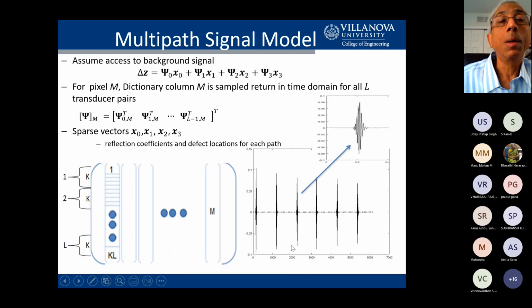Well, again, for each path, you construct a dictionary matrix. And for each path, you have a defect unknown vector. Of course, these X0, X1, X2, X3 must all be identical because the defects are always at the same spot. They don't change just because the path of the wave changes. So you exploit that idea.